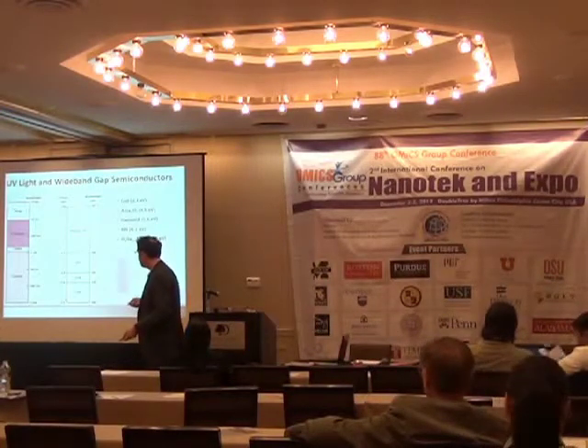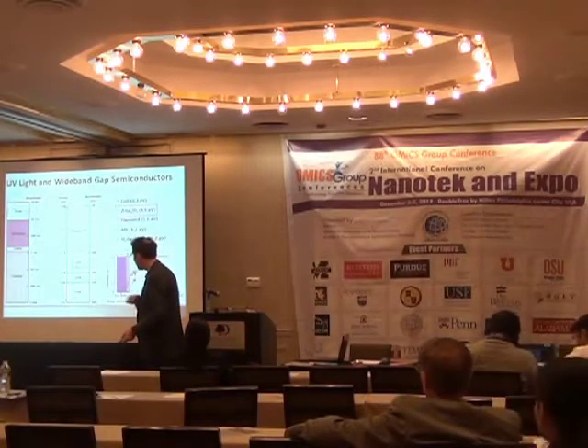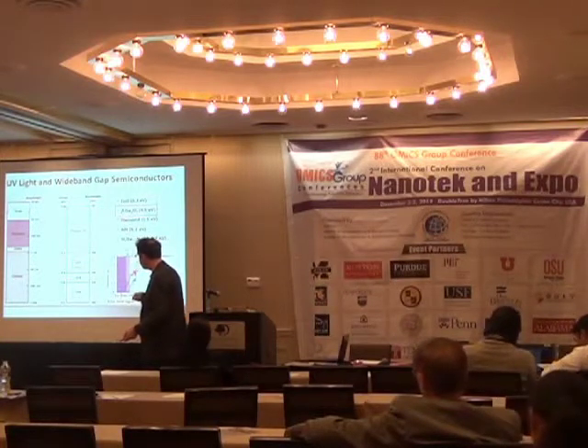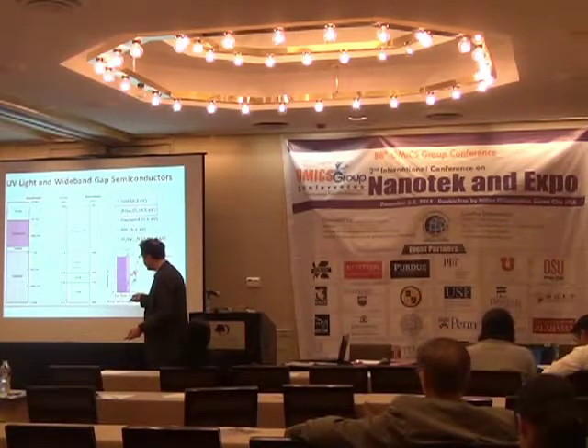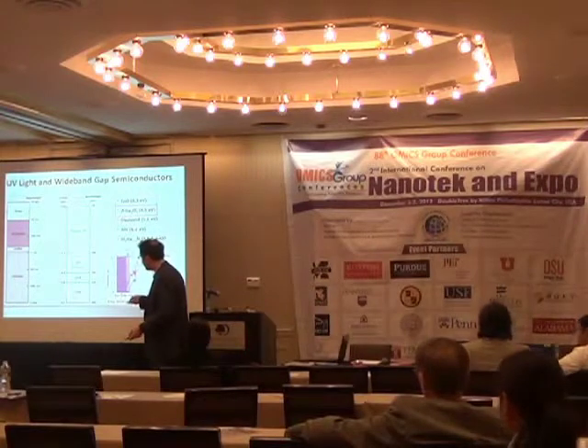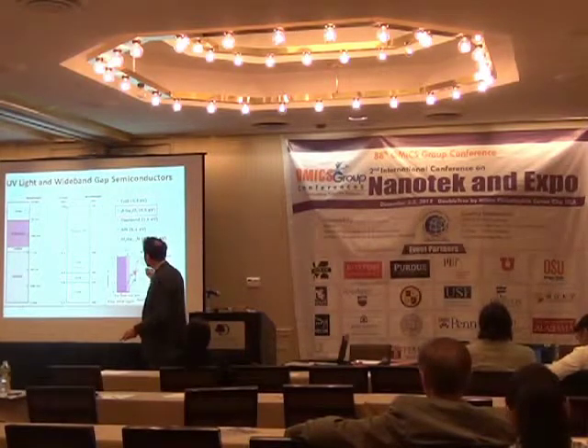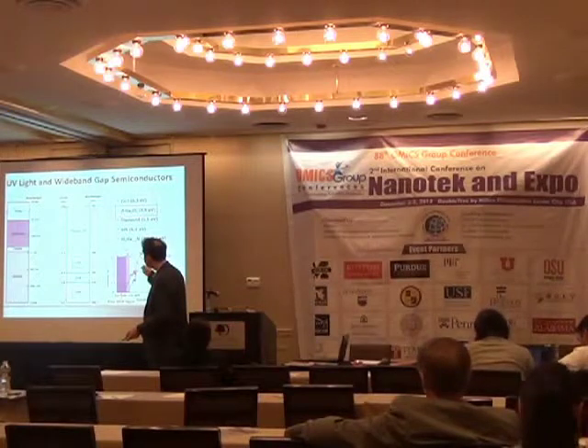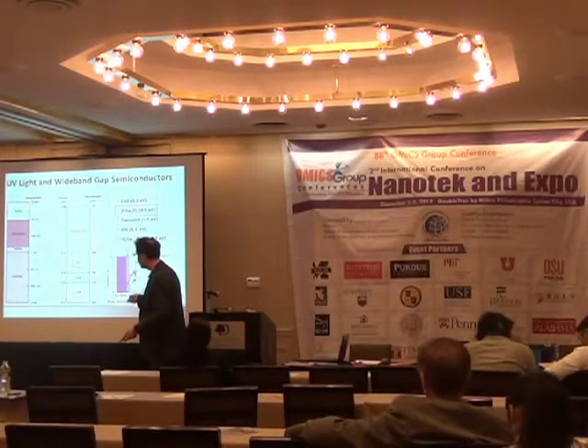Okay, so you all know very well about UVA. UVA is between 400 and 320 nanometers. To detect the light selectively, you need a band gap of 3.3 electron volts, and zinc oxide has exactly that band gap. So zinc oxide is a good material to detect UVA.